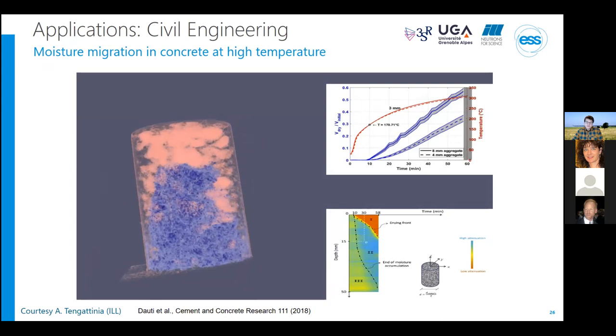Besides gaining an improved understanding of the process itself, the colleagues were also able to verify a hypothesis related to an accumulation of moisture ahead of the front, which eventually is responsible for a pressure buildup that can result in the spalling of the concrete, and in the worst case can then cause collapse of full buildings.